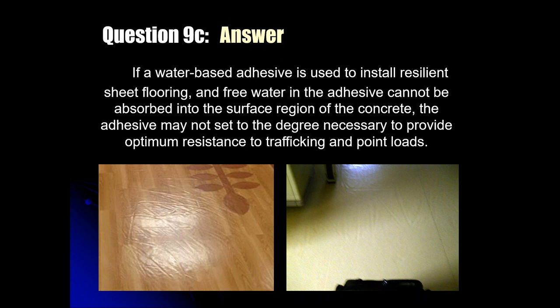Everything looked great, but because the surface of the slab had been power troweled to a burnished, dense, non-porous finish, that free water was not readily absorbed. Everything looked great when they installed it and rolled the floor. But what you're seeing on the left is right in front of the elevators, in the turning arc where the gurneys and other wheeled transport equipment make their turn onto or off of the elevator. And that adhesive never achieved the degree of hardness or set that it was intended to.